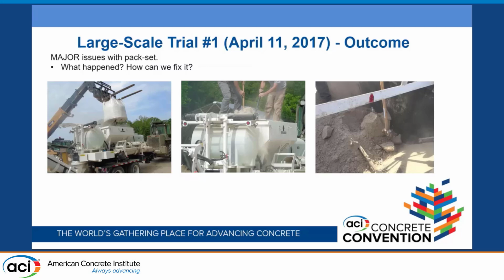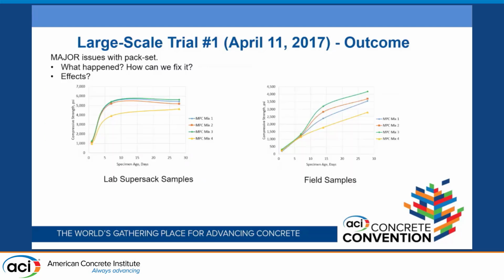We went ahead and did our best, as you could see on the previous slide, but we did not get the strength results that we wanted. And so how is this pack set happening? So, this is our lab test results. This was the field test results, much lower strength, sort of a curve that doesn't make too much sense. It's not a normal curve.